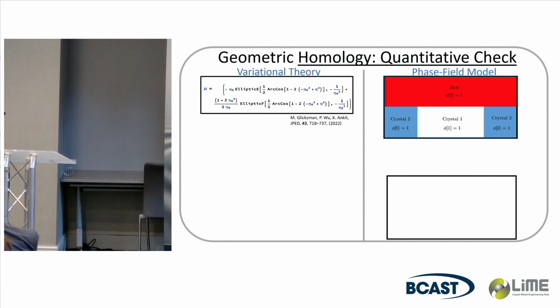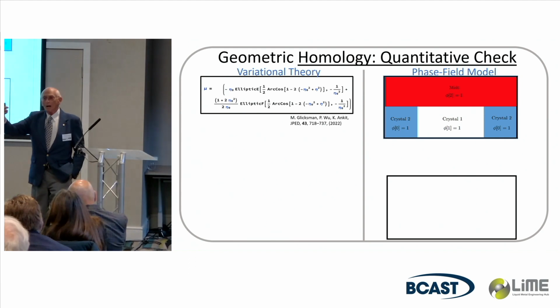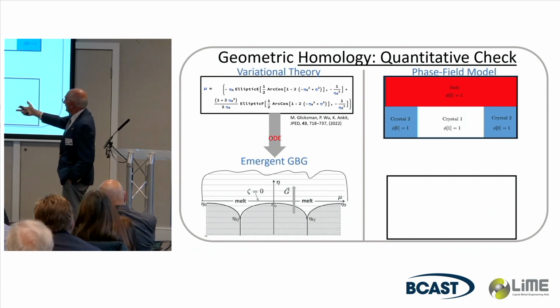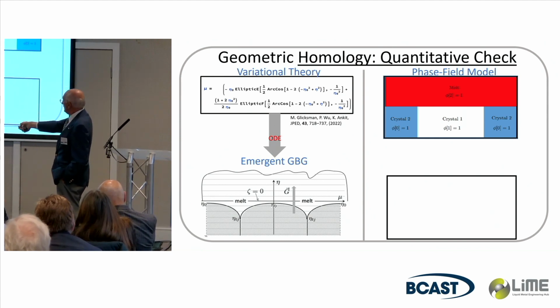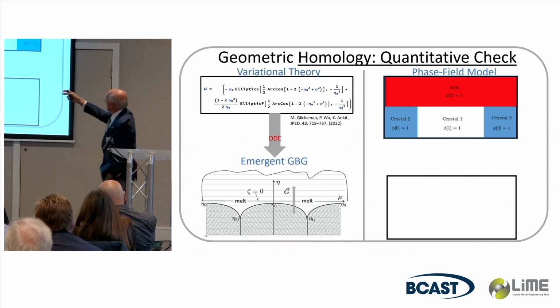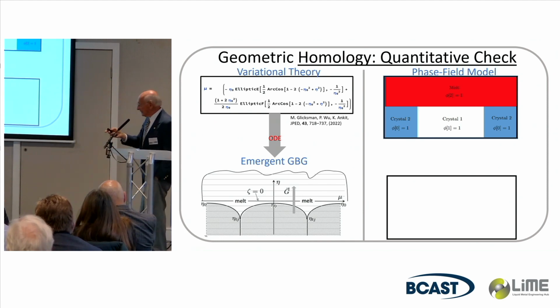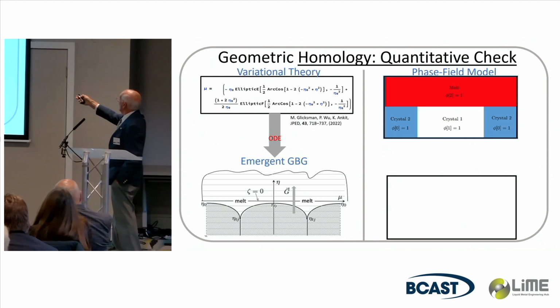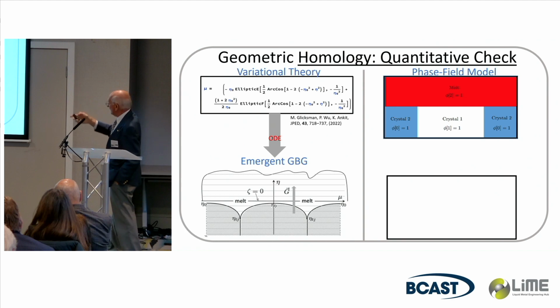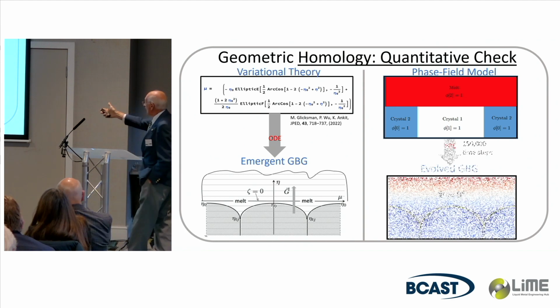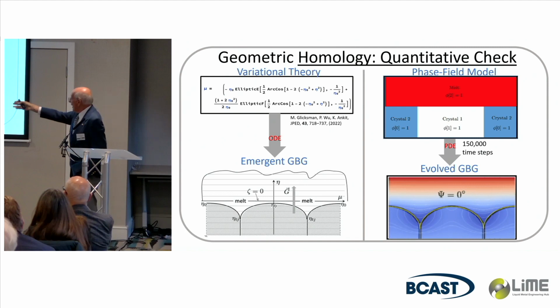This was just published at the end of last year with my colleagues Wu and Ankit from Arizona. You start off with the equation of the interface, and it emerges immediately into basically the shape of the solid-liquid interface. On the phase field model, you run numerics, and you start off with an initial state. First, you've got to prove it is stable, and that quickly develops into essentially a comparable interfacial shape.